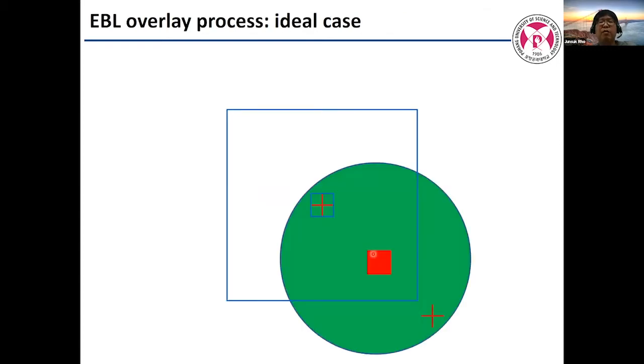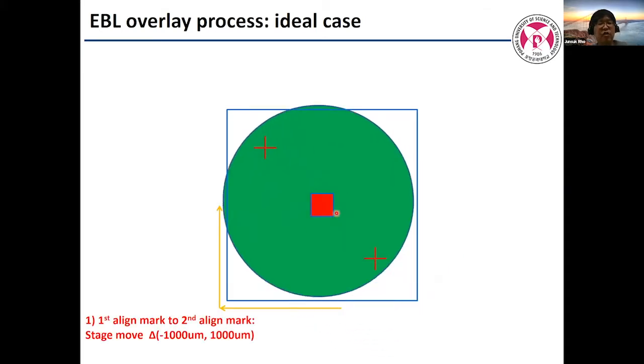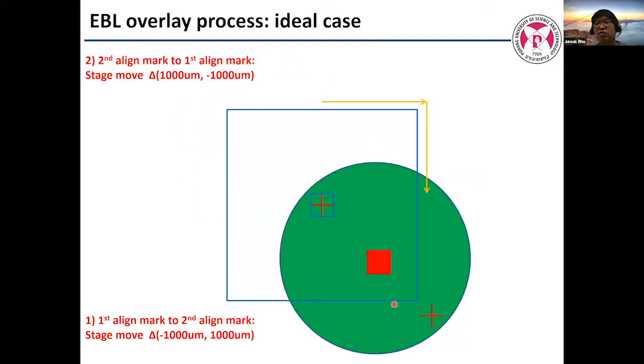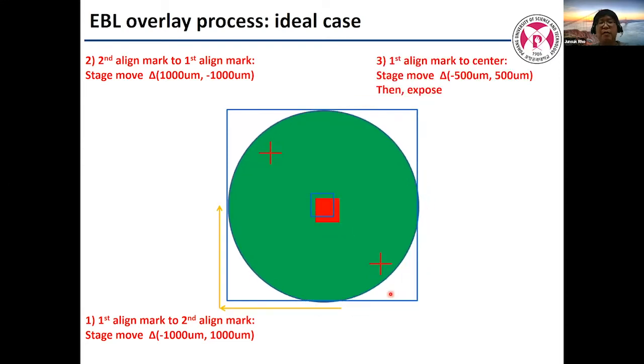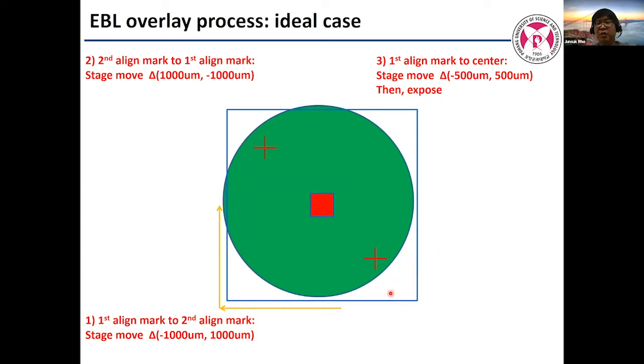But the problem is e-beam lithography. We are not allowed to see whether the alignment is good or not, because the scanning electron microscope is used as a microscope and at the same time as an exposure tool. So we cannot directly align them. So indirectly, we use a virtual alignment mark. At this moment, alignment is assumed good, but we are not allowed to see. But anyway, we do the exposure. After this process, we do deposition, lift off, and check by SEM. It's not an easy job, but we have a pretty good alignment skill. We did this coordinate compensation of the stage, plus some experience. So about 20 nanometer overlay misalignment with about 70% yield success ratio.